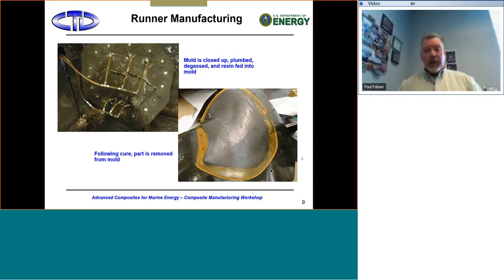And so these are just a couple more pictures. This shows the blade mold after the resin has traveled through the tubing. This is high temperature Teflon tubing, and then the resin has come out of the mold. And on the right-hand side, you see after the cure, we remove the top part. So this is what the blade looks like after you pull it out. And so you see that you have the resin flash around the outer surfaces or outer edges of the blade.